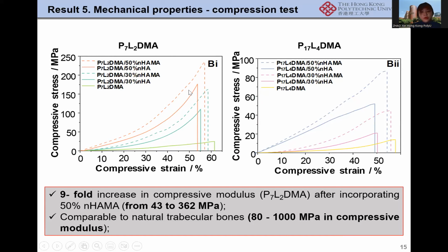And by using different Ms and Ns, changing the concentration of the polymer and the hydroxyapatite nanoparticles, and changing how much HA we add to the nanoparticles, we can greatly change the mechanical properties of the polymer. And we can make these materials within the compressive modulus range of trabecular bone.